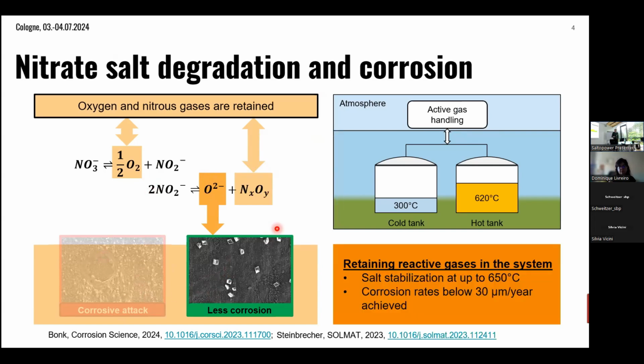In lab scale, it could be demonstrated that salt can be stabilized up to 650 degrees with this method. Also, corrosion rates well below 30 micrometers per year could be achieved. So that's the idea of how we can actually increase the temperature.